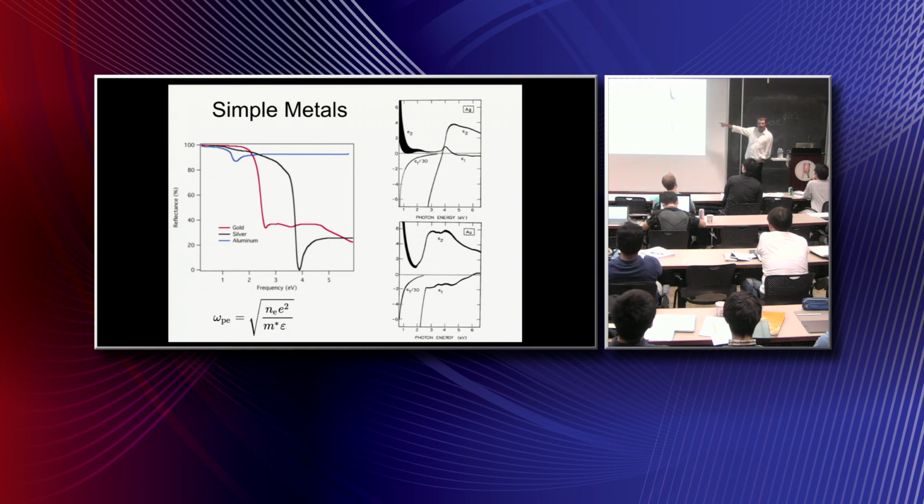If you take this data over a very large frequency range, from the lowest frequencies you can to the highest frequencies you can measure, you extrapolate it, and you perform Kramers-Kronig relations, you can get the phase out. From that, you can figure out, let's say, what the complex conductivity or the complex dielectric function is. That's what's shown here, for instance, this is for silver, and this is for gold. And you can immediately see from this data why gold looks different than silver.